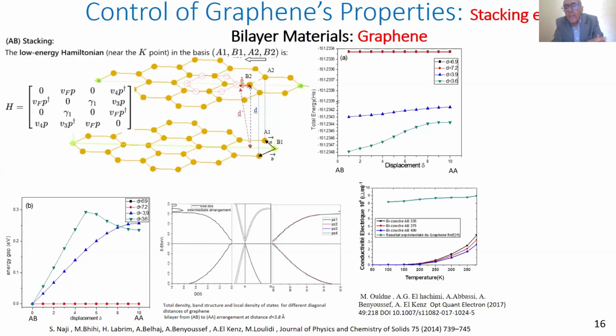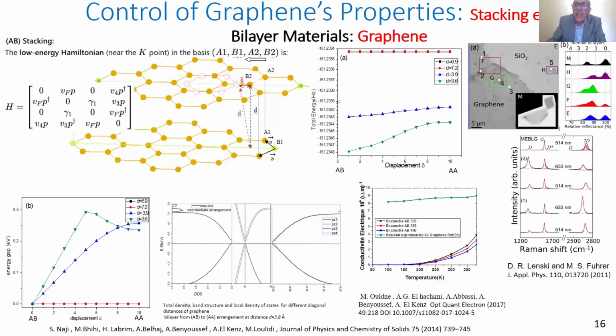And for this, we can see that for AB stacking, there is a semiconductor behavior and an increase of the electrical conductivity versus the temperature. This many-layer graphene has been observed experimentally, and the characterization using Raman shift shows the shift of the peaks depending on the thickness of the layer. So it is important to move from semi-metal to semiconductor by increasing the number of layers from monolayer to few layers. But it has been observed that we can do better than that.